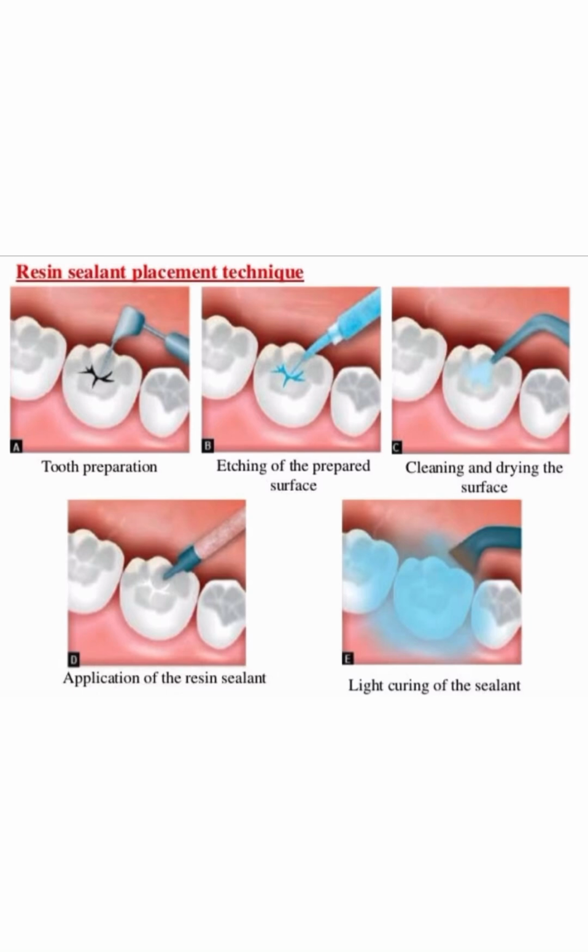How do glass ionomer sealants differ from the normal sealants? In glass ionomer sealants, we do not etch the surface, we just clean the surface and use a conditioner. Which conditioner? 20% polyacrylic acid. And then we run the glass ionomer into the fissures, and we protect the material during initial setting. After applying glass ionomer, we apply unfilled resin, petroleum jelly or fluoride varnish to protect the material.